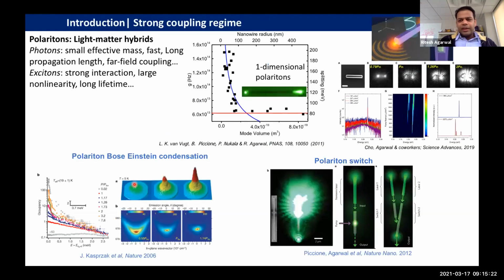Okay, so again, initially our work was on nanowires. So you can imagine nanowires with diameters of the order of 100 or 200 nanometers. So very strong confinement along the cross section, but extended along the third dimension. And we showed when the nanowires are large, the light-matter coupling strength matched that of the bulk material.